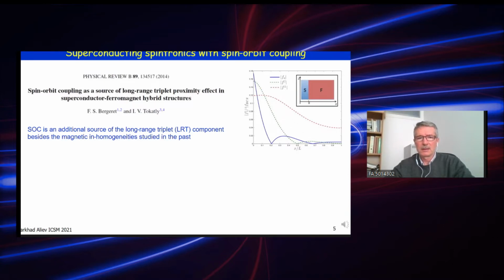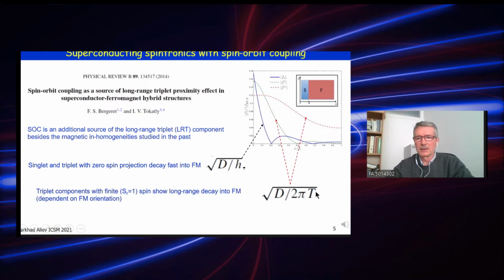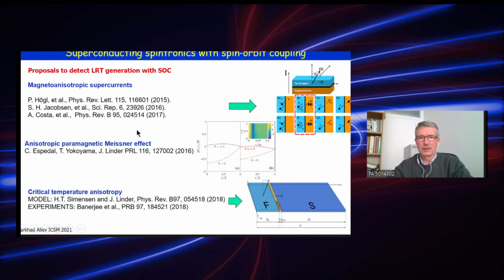Here is work by Sebastian Bergeret and Tokatly, where it is clearly seen that, depending on the orientation of the exchange field and ferromagnet, we can have or not have long-range penetration from superconductor to ferromagnet. This is inversely proportional to temperature, so it's really an effect which is not just restricted to the decrease of TC.